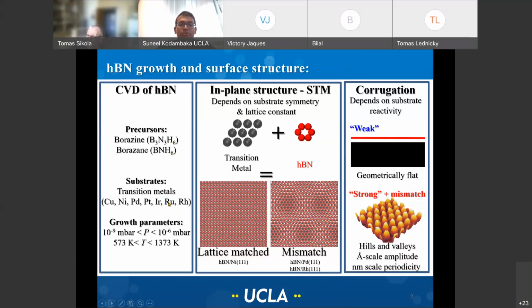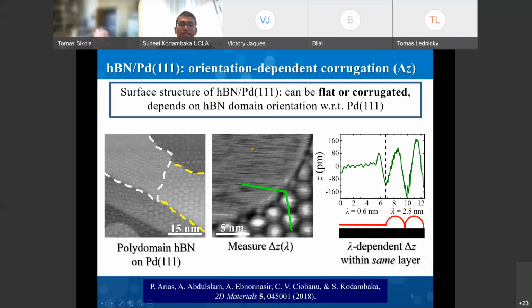And the typical substrates people have used are transition metals, which act as excellent catalysts for the decomposition of borazine. And depending on the type of metal you use, you may obtain commensurate structures or moire patterns. And the surface roughness, or the surface corrugation, depends on the interaction between the layer and the substrate. And in our experiments, we found that for hexagonal boron nitride on palladium, not only does the moire periodicity change with the orientation of the domain, but the corrugation amplitudes also change. We also happen to observe similar moire pattern periodicity, but significantly different corrugations, which we interpret as weakly interacting and strongly interacting domain formation. So it's a bifurcation of the domains on palladium 111.